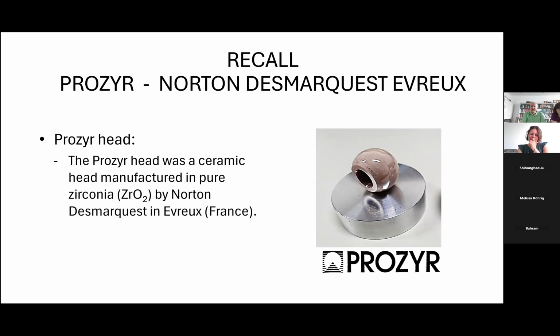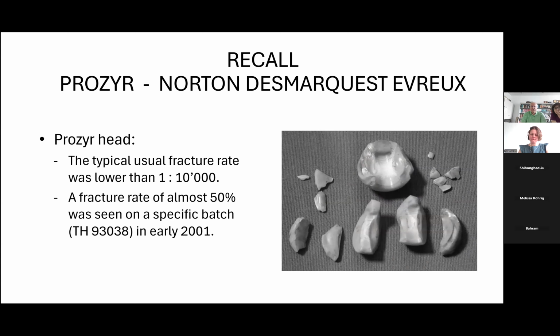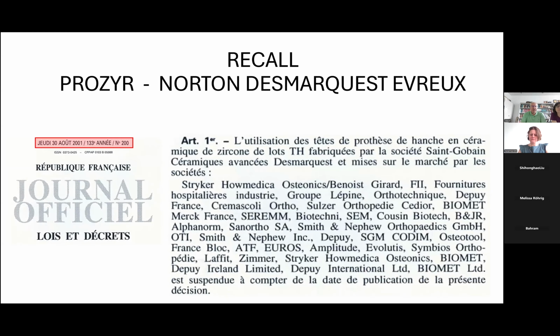Another example, which has nothing to do with orthopedics, with corrosion, sorry. It was a ceramic head, which was in zirconia, and it was a small manufacturer in France, in Évreux. And they changed the type of furnace they were using in order to make the sintering of the ceramic head. The fracture rate was, with a good furnace, 1 in 10,000. And suddenly, on one batch, the fracture rate was almost 50%. If you take the Journal officiel de la République française, the national journal of the French state, they were saying all the implants made with this type of furnace have to be recalled immediately, and it is impossible to be sold in France.